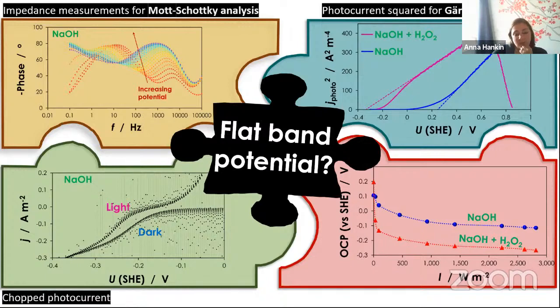So if you make a measurement, how can you know whether it's got error in it or not? Another one is chopped photocurrent, which is my favorite one. And also this open circuit potential. The theory being is that if you shine really, really high intensity light on a semiconductor, the bands will unbend automatically. And so if you measure the potential at high intensity, that should be your flat band. But as it turns out, that's not necessarily the case.